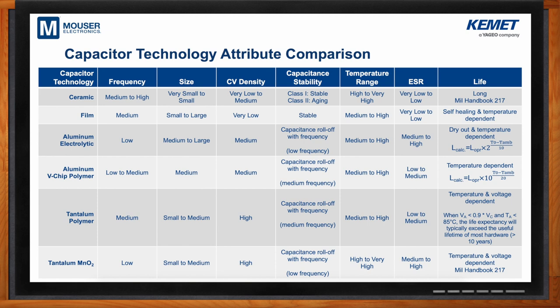Then you've got kind of a newer entrant into the market, and that's polymer technology. And there's really two polymer technologies. You've got aluminum polymer, which are surface mountable V-chips. And then you've got tantalum polymer, and there's a lot of similarities between the two technologies, with the polymer system used as the cathode. The anode is different between the two. One is aluminum and the other one's tantalum. The tantalum has the advantage of giving you a greater CV density than the aluminum polymer. The aluminum polymer does offer some larger capacitance values than you can get with the tantalum polymer simply because the parts are physically bigger. And you can also go higher in voltage in the aluminum polymer. We've got some that go actually all the way up to 250 volts, not in surface mount, but in radial.